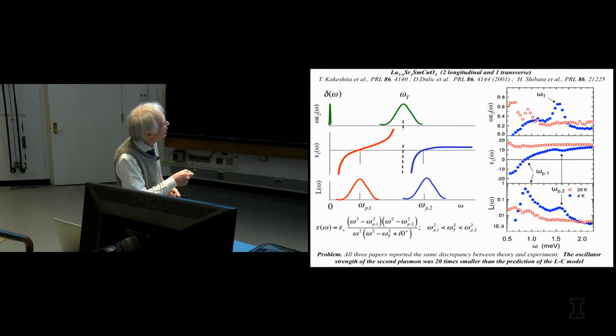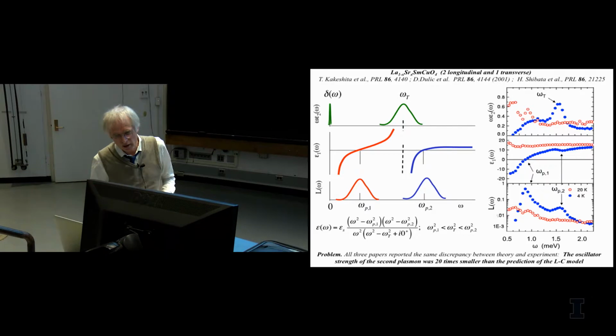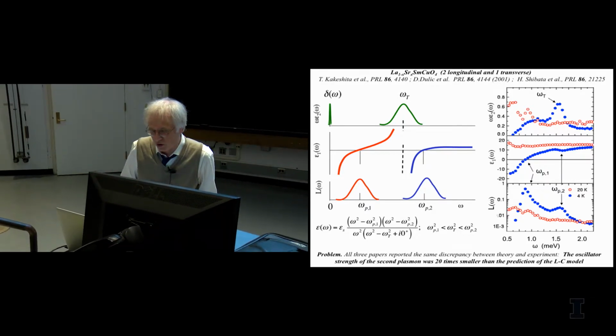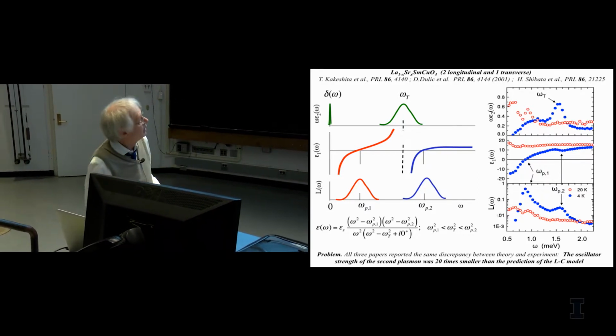And this would be a zero crossing were it not that there is a sort of a damping, so it's only a small wiggle. If you calculate the loss function, it gives 2 peaks. However, in all 3 papers, it was noticed that this peak here was 20 times smaller than that peak. Note, this is actually a log scale. Just to make it visible, you have to plot it as a log scale, and this is way too small, a factor of 20, and that was actually seen in both cases. So actually the agreement wasn't so good, it's just that we saw the 2 modes.